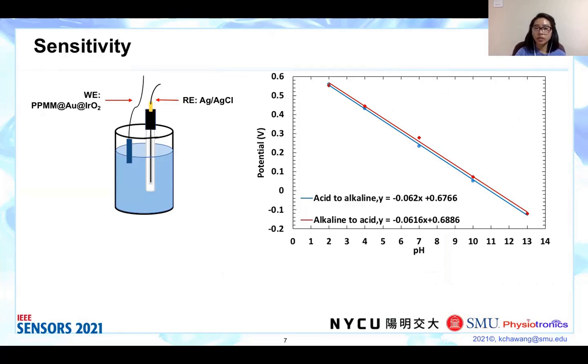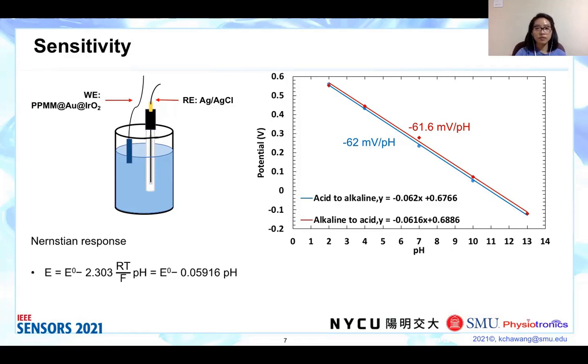We observed super-Nernstian sensitivity of 62 millivolt per pH for the acid to alkaline path and 61.6 millivolt per pH for the alkaline to acid path. The super-Nernstian responses for both cases show good quality of iridium oxide deposited. Ideally, Nernstian response is 59.16 millivolt per pH, but sensitivity can also be affected by oxidation states of iridium or ion exchange mechanism on the electrode surface as described by the equation, and thus produce super-Nernstian sensitivity.